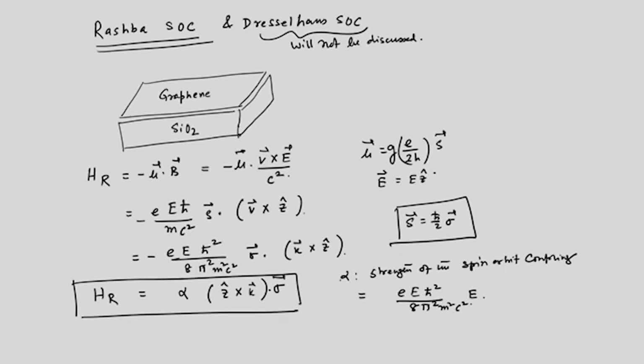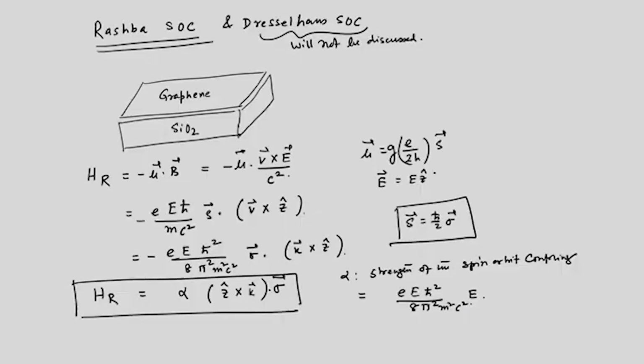So, alpha can actually be increased, and several organic electrolytes etc. are being used, or adatoms like heavy adatoms such as gold on the graphene matrix. They have been used in order to locally create a charge imbalance, which gives rise to a gradient of V, and hence an electric field that will give rise to this coupling. This gradient of V is of course in the z direction, and the inversion symmetry is broken in the z direction.